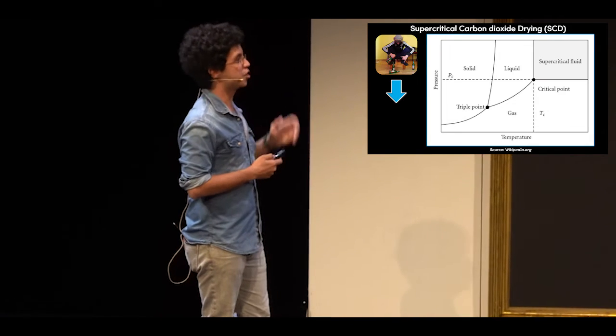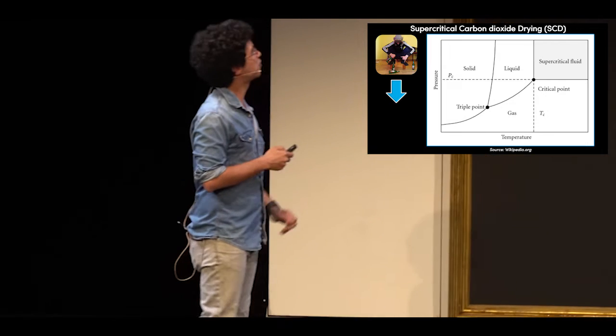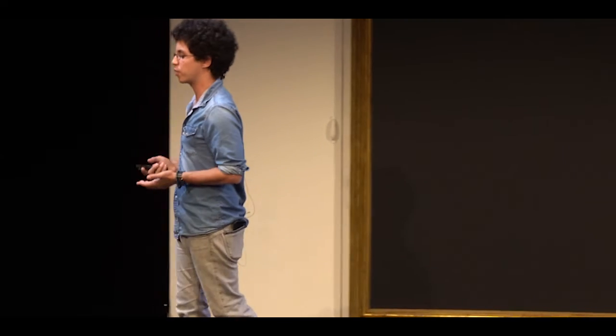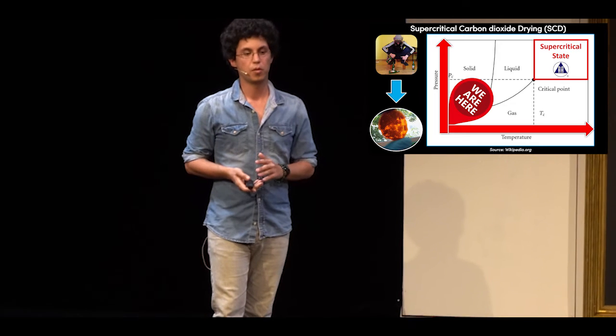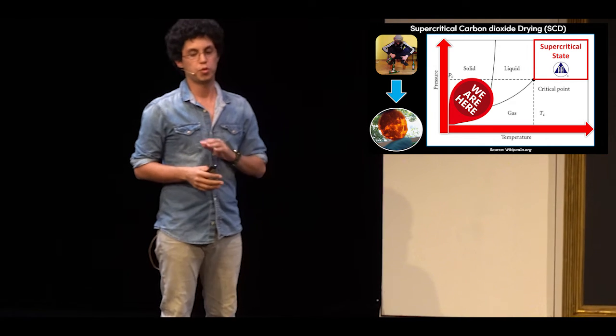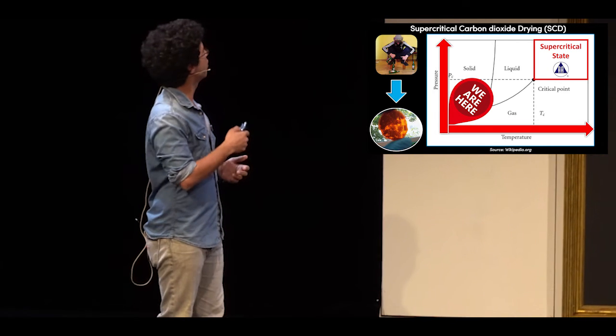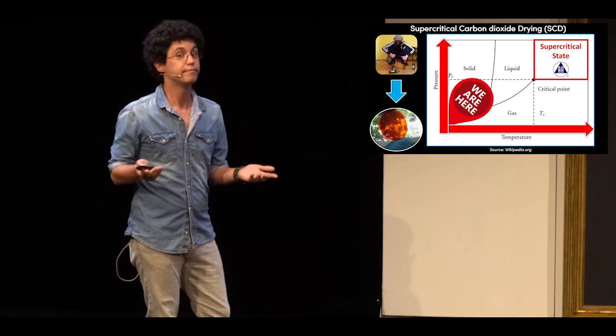And then you have one final step. You need to go from the alcohol to some other place. So we need a map. But this looks crazy, right? But don't worry. We are here. What we are going to do is increase both the pressure and the temperature, and we will reach a secret place called the supercritical state, right over here. This place is sponsored by the Alcoholics Anonymous, so you cannot bring alcohol, you just air, okay? So you had your alcohol, hello, and you replace all the alcohol by air, so you have an aerogel.